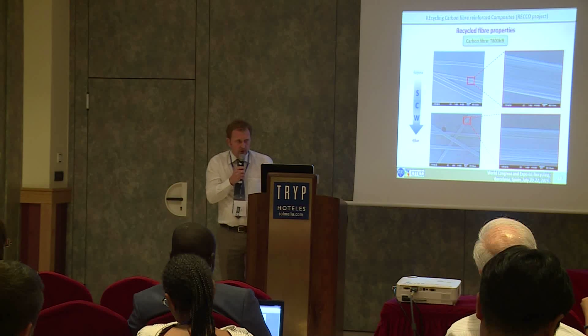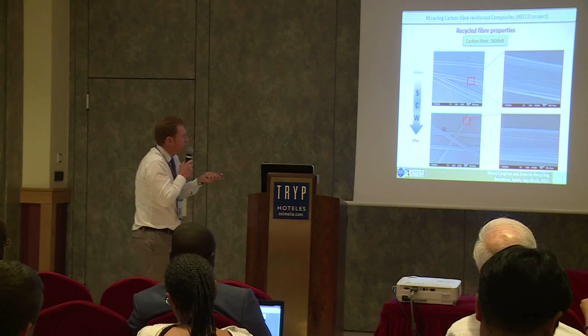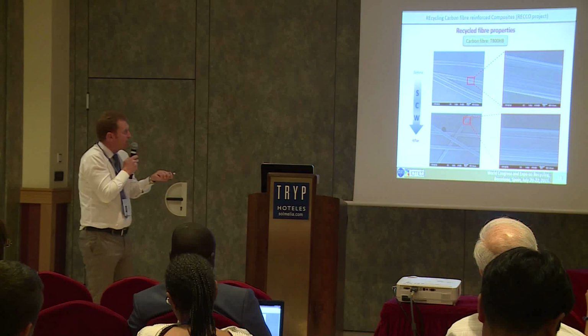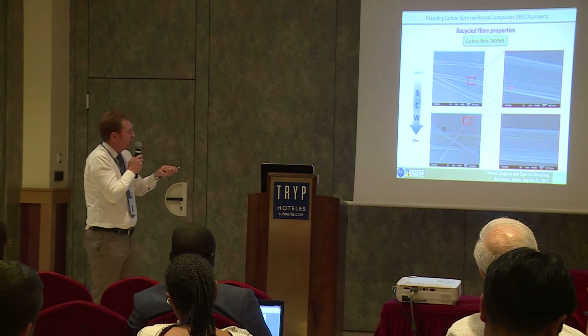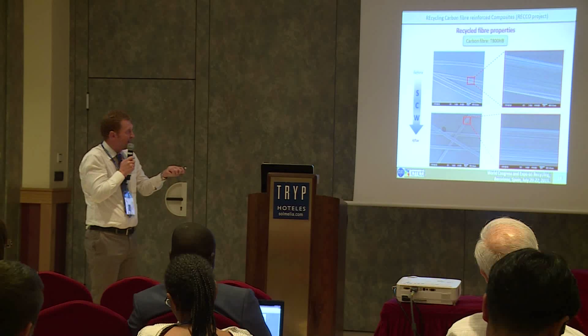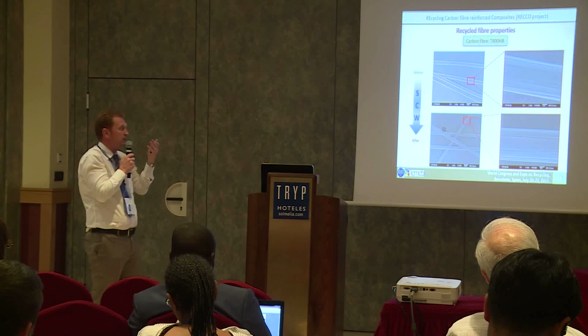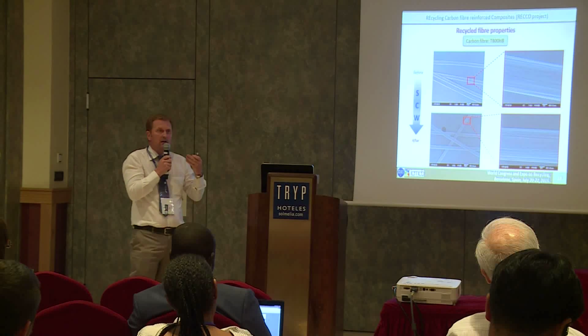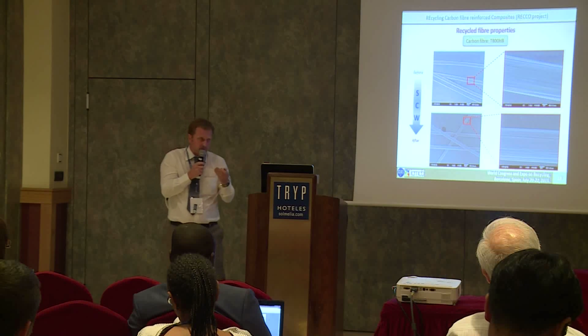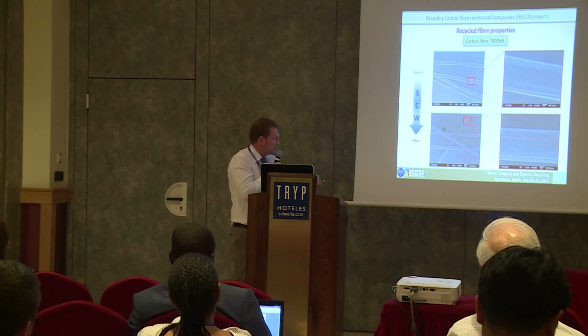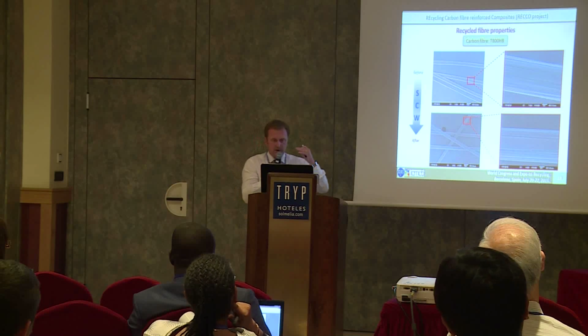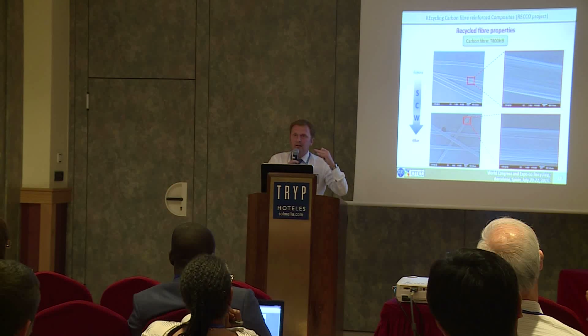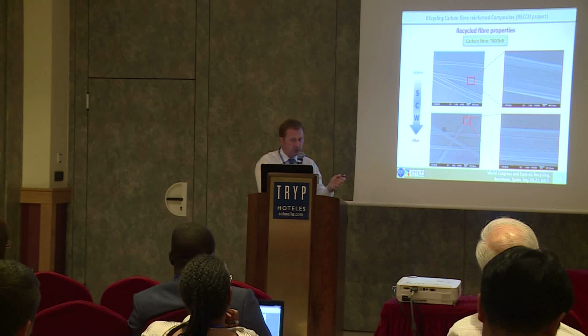In terms of characterization, you see here some scanning electron microscopy pictures of the fiber before making the composites, and here the fibers after the recycling treatment. And what you can see is that there is no destruction of the surface of the fiber. The surface of the fiber is very clean and is the same as the one before the treatment.